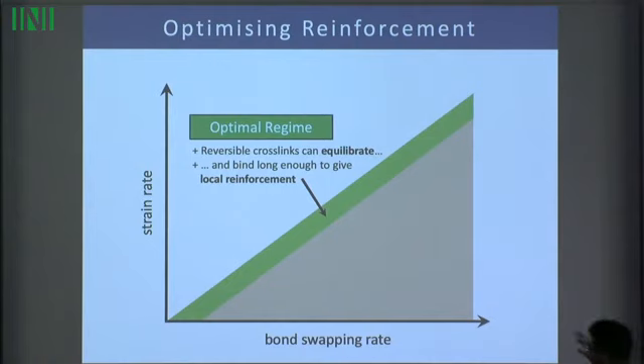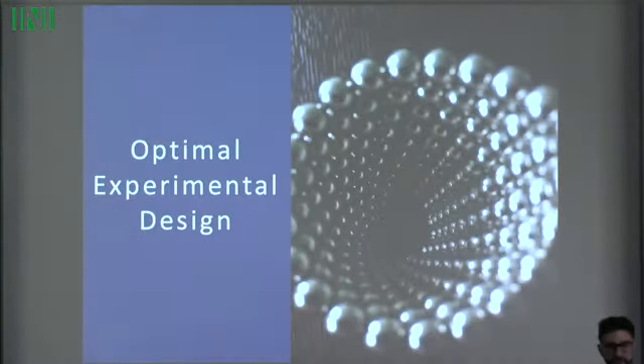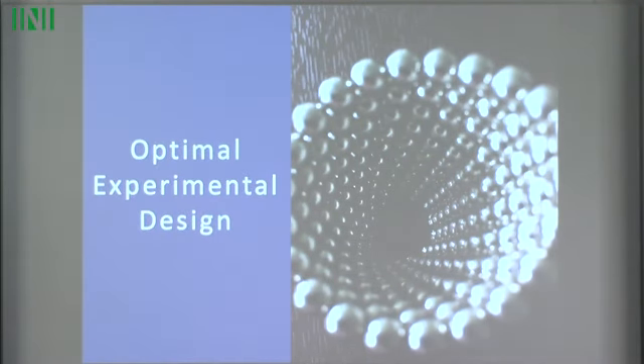And so I expect, and I don't have proof for this yet, but this is actually the subject of some ongoing work, I suspect there's a sweet spot in there where we've tuned the kinetic lifetime of these bonds so they're long-lived enough to bear mechanical strain on a time scale that's sufficient to make the material tougher, but they're also rearranging fast enough on the strain time scale to effectively cluster around the permanent crosslinks. Okay. So I've mentioned these different optima. So there's this weak binding free energy optimum for the clustering, but there's also this optimum kinetic regime. And so how do we get that in experiment? Because they seem a bit contradictory, perhaps.